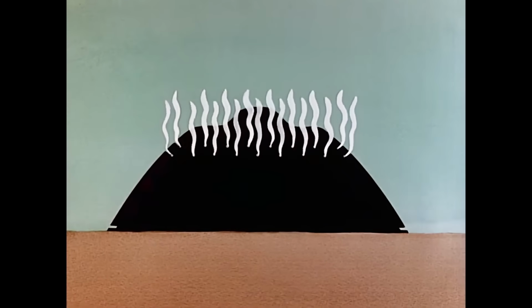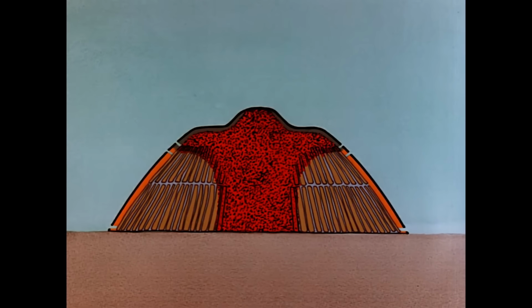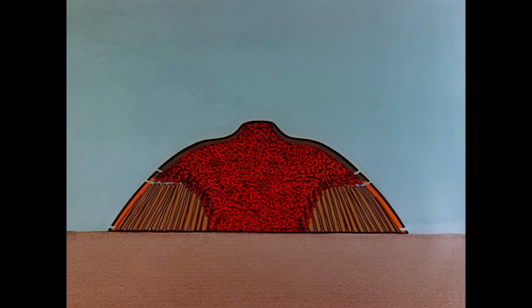Back to the cross-section. As the mound's diameter increases, each layer takes up to 12 hours to char completely. Wood condition and weather also play a role. As volatile compounds are driven off, the kiln changes shape. The charred wood shrinks both lengthwise and around its girth. Each day the mound loses about half a meter of height. By the time it's emptied, its volume will have shrunk by 55 to 60%.